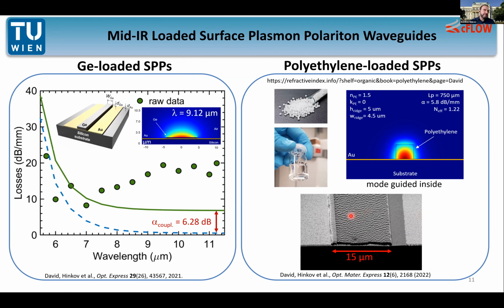which helps to realize and to define those stripes that we did instead of germanium, now with polyethylene. And polymers, everyone who has worked with polymers knows, are very nasty. And Mauro David, who is one of my PhD students, and the team did a tremendous job developing this process. And it has now one huge advantage, at least for certain applications, which is that we can make the polyethylene very thick and guide the mode inside, still having relatively low losses. So in contrast to the germanium on top, where the mode is outside, in polyethylene the mode is guided inside. And now we're going to see how we can really exploit that for two different types of applications.